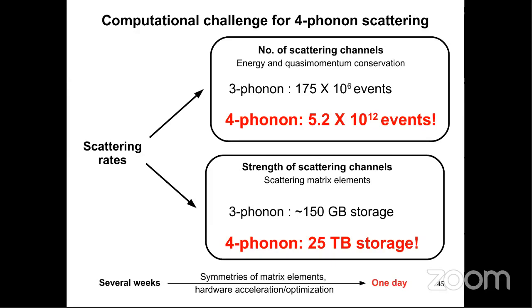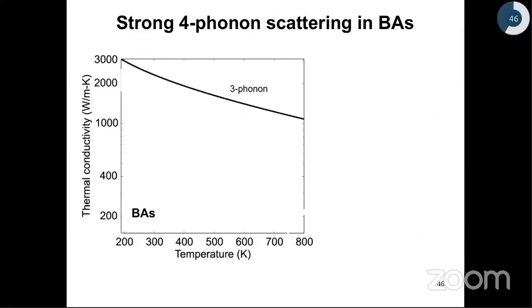So having spent so much effort trying to improve the speed of the calculation, let's see if it's worth it or not. So here, just to refresh your memory, I'm showing the thermal conductivity of boron arsenide calculated using the 3 phonon conventional picture. So you can notice that at 300 Kelvin, the thermal conductivity exceeds 2000 watt per meter Kelvin. That is almost as high as diamond.